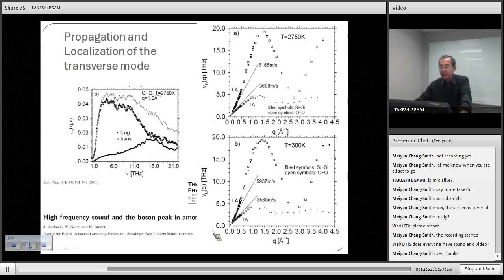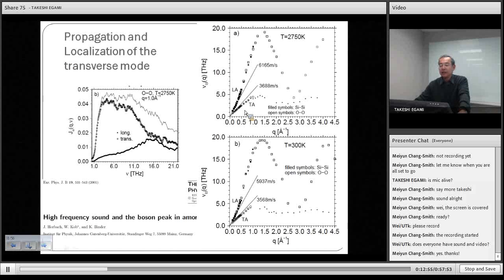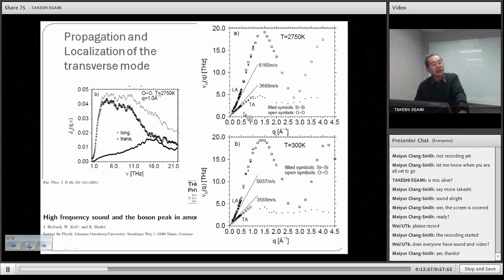So that's the typical phonon dispersion in glasses. It's a silicate glass, and the transverse acoustic phonon becomes localized, while the longitudinal acoustic phonon goes like that. Okay, and each one of them is shown by a single ball point, but actually it's just a peak position. The phonon is very, very broad, like that.